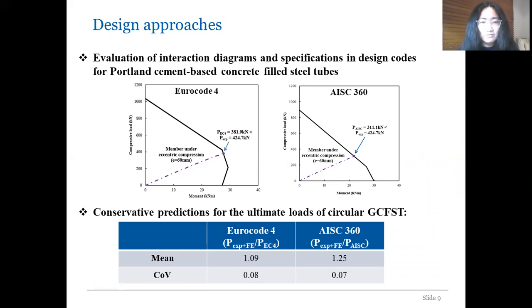The interaction diagrams from Eurocode and American standards are shown in the two figures. And I demonstrate an example of the design load estimation for a specimen tested on the eccentric compression with eccentricity of 60 mm, as shown in the figures. So you can see that the design loads from Eurocode or American standards are lower than the ultimate load measured for the specimen in experiments. So this indicates that the existing design methods can be used to generate conservative strength predictions.